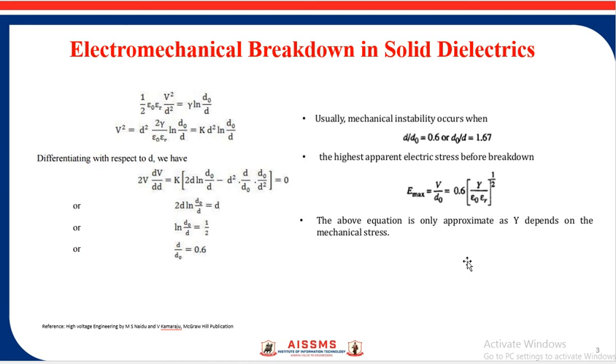That means at this stage, breakdown will occur. Recently, this theory has been modified based on the concept of fracture mechanics. In the new mechanism, filamentary shaped cracks propagate through the dielectric material, releasing both the electrostatic energy and the electromechanical strain energy stored in the material due to the applied electric field.